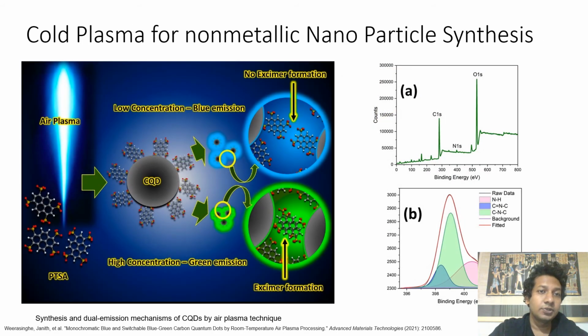Cold plasma reactions are used to synthesize non-metallic nanoparticles such as silicon nanoparticles, silicon quantum dots, germanium quantum dots, carbon-based nanoparticles such as graphene, carbon nanotubes, carbon quantum dots, carbon nanodiamonds, and fullerenes. This is a synthesis technique for switchable blue and green carbon quantum dot synthesis, which is assisted by air plasma. The starting material is an aqueous solution of pyrene tetrasulfonic acid tetrasodium salt hydrate. This technique is highly efficient, and the synthesis process can be completed within a few minutes.